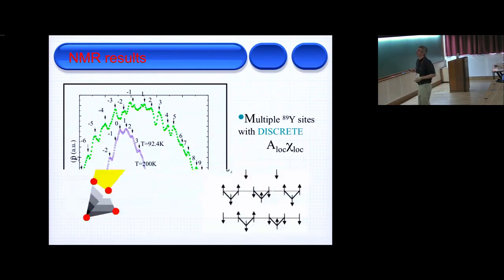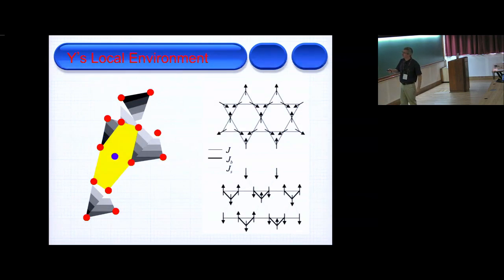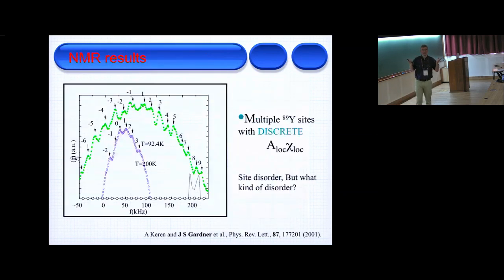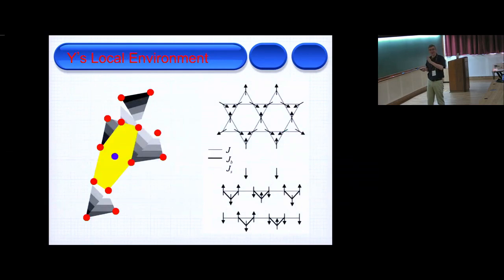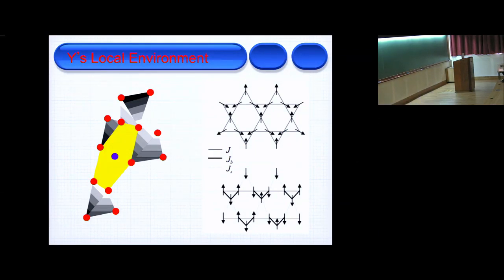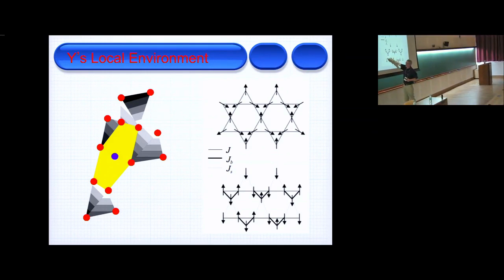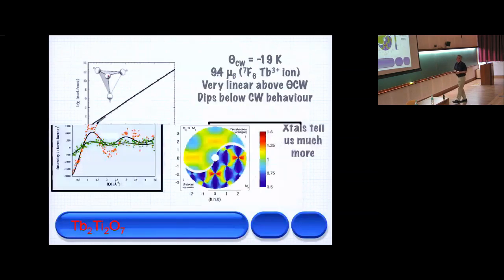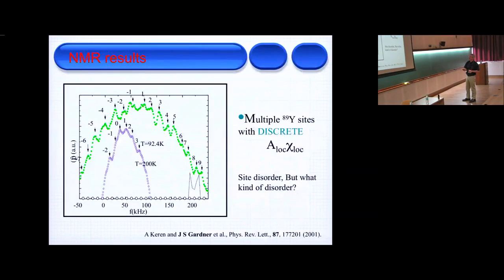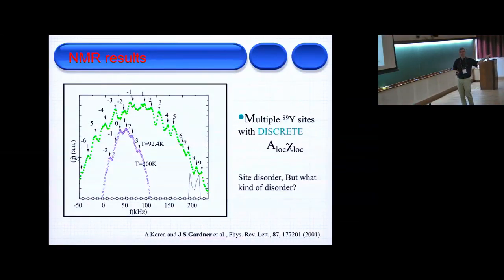Yes. So, in this cartoon here, I've basically only shortened these, but the length must be different for many of these bonds. We still don't really understand it, but it's discrete. So for some reason, it's going to a well-defined position, but there are many of these. If you imagine this spin here, it basically can move in discrete positions up and down here. You're changing the J or the fields that you will experience in this environment, and you're getting all those peaks. And as that data showed, as you cool down from 200 Kelvin to 92, where remember the transition is at 22, we imagine these correlations are building up, the strength is increasing, and you're able to detect more features.